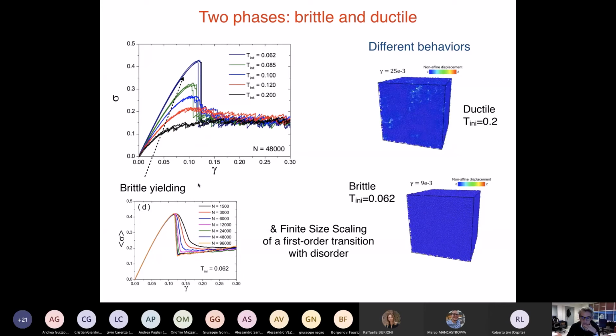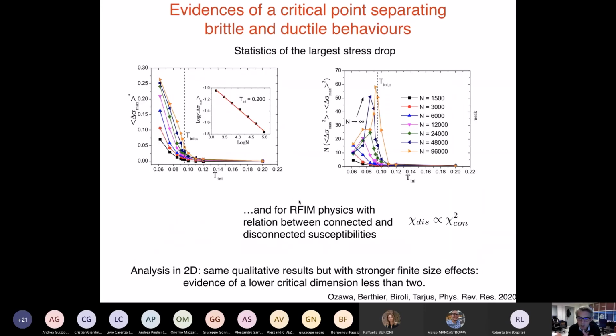All right, and we also can compare this discontinuous susceptibility to what is called the connected susceptibility. And again, we find something very similar to what you find in the random field Ising model: the disconnected one, which is the fluctuation due to the disorder of the order parameter, actually scales like the square of the connected susceptibility. This seems to say that this critical point that separates these two different ways of yielding is very similar to the one that you find in the random field Ising model, and that it should be related to a zero temperature fixed point.